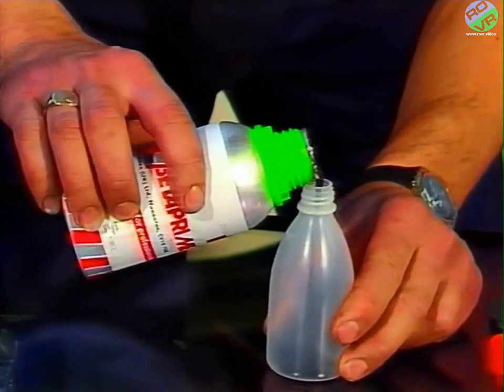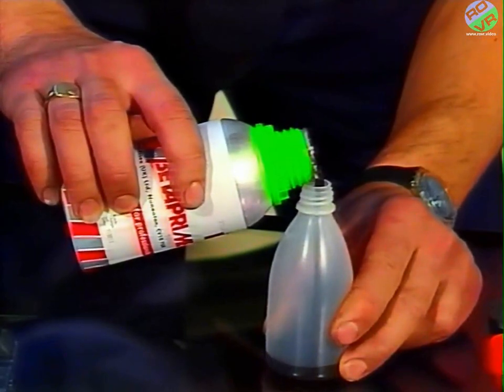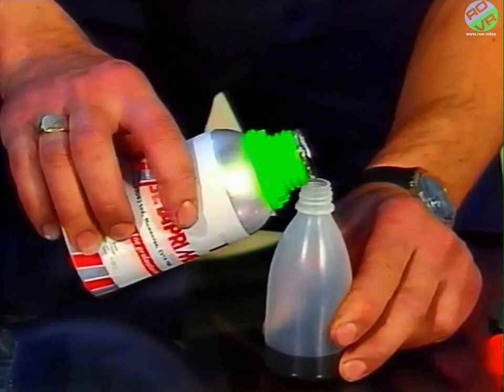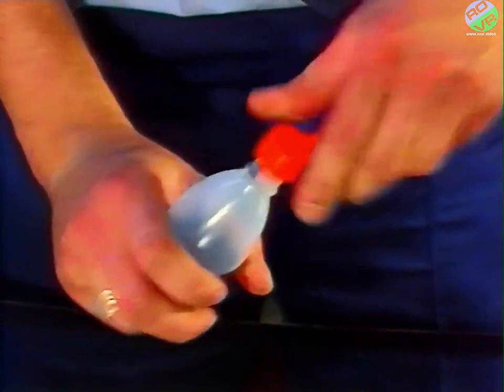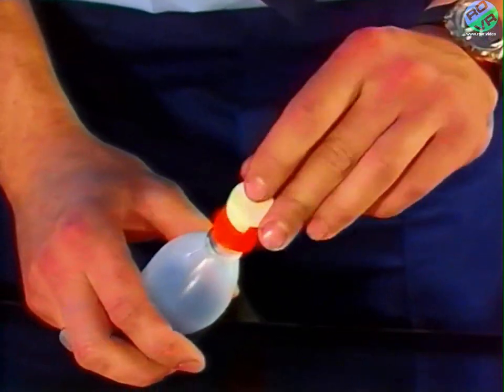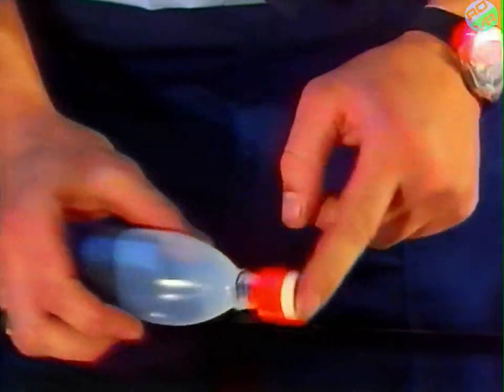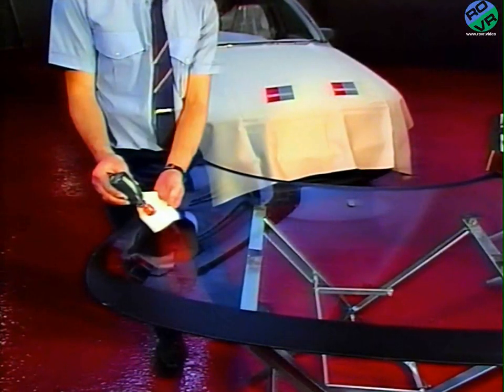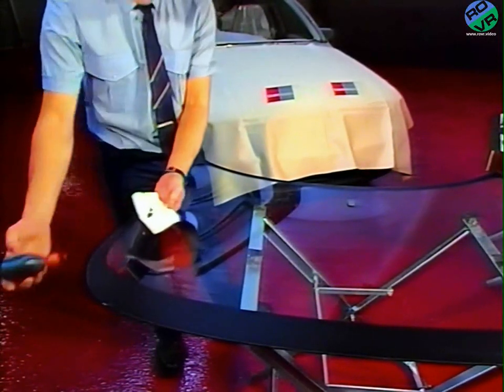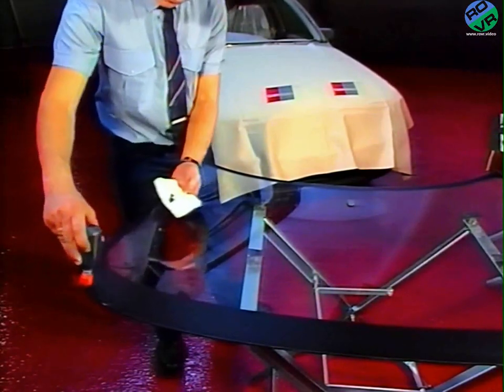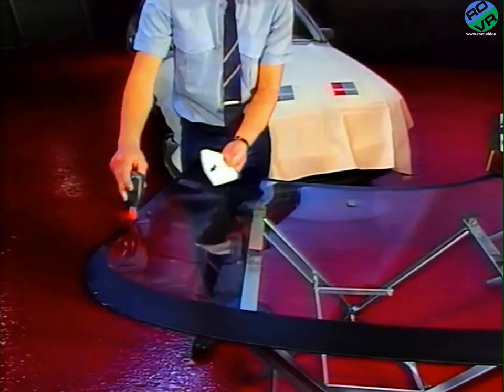As soon as you've done that, get hold of the Betaprime 5001 glass primer and shake it for at least a minute. The best way to apply the primer is to use the Gurit Essex applicator bottle and felt, but you can use a wire felt instead if you prefer. Polyurethane adhesive should never be applied to wet primer, so the object is to apply the primer in a thin, even and quick drying film with a continuous flowing movement.